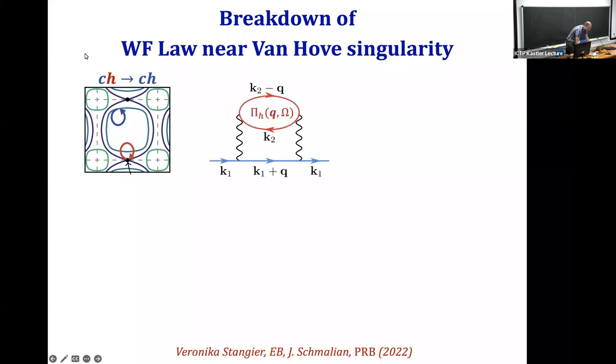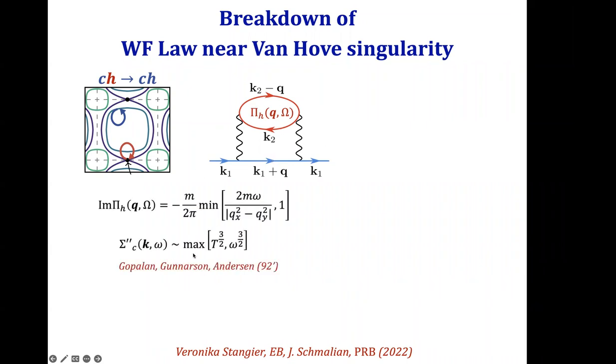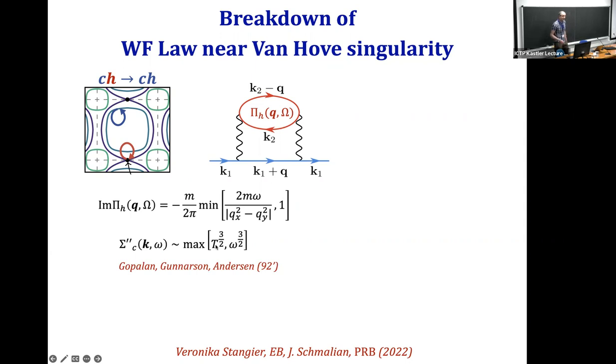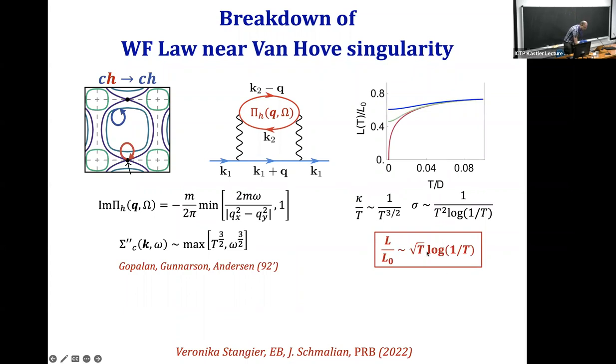So we calculate the cold electron cross section to scatter off hot electrons, which is described in the diagram, and that turns out to scale like T to the power 3/2. Okay, so very different from the usual Fermi liquid behavior, which is T squared. And if you calculate the thermal conductivity, kappa over T, that scales like 1/T^3/2. So it is dominated by these processes. You compare that to the electrical conductivity that goes like 1/T² log T. So the ratio, which is the Lorentz ratio, scales like √T (log T).